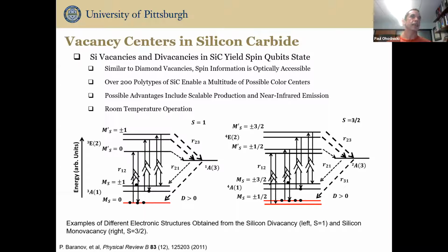Another example of a material system that looks promising is silicon carbide. So these have a number of different types of defects which can form color centers, which can create possible opportunities for qubits with different characteristics. The most commonly explored so far are silicon vacancies and divacancies. One of the advantages in this case that we've seen in looking through the literature is there do appear to be certain types of color centers where you have less cross-sensitivity to certain variables. So you may see sensitivity to magnetic field, but not as much sensitivity to some of the other variables. Because of the large number of polytypes of these materials available, as well as the fact that there does seem to be some degree of selectivity, these are materials that are of interest moving into the future.